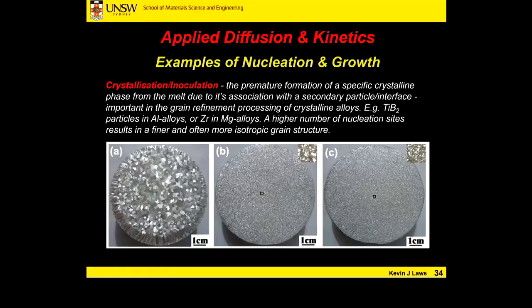Something else we're going to talk about, we've got 15 minutes to go, is inoculation. We've brought it up a little bit earlier, but inoculation is the premature formation of a specific crystalline phase from the melt due to its association with a secondary particle or interface. So this is heterogeneous nucleation, and we're doing it on purpose. One of the best examples in industry is the inoculation of aluminium alloys.